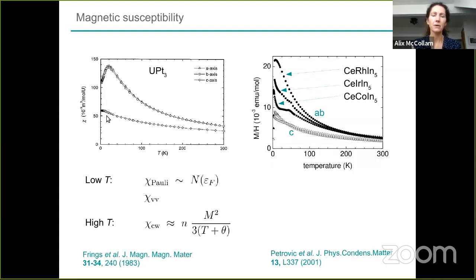There's also a Van Vleck contribution to the susceptibility. So the low temperature susceptibility is not necessarily unique, as I said. It doesn't always saturate in a nice Pauli-like behavior. You can see different things going on. This was quite reasonably well understood in uranium platinum 3. The Van Vleck contribution kind of explained the large size of this and the behavior here.